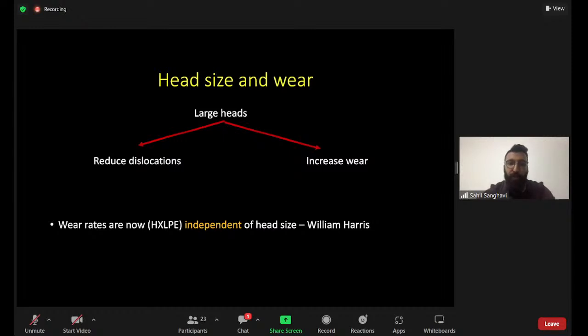Now, the main problem here with polyethylene was the correlation of head size and wear. As we all know, when you use a larger head in total hips, you're always tempted to use a larger head because you know it's going to give you good stability and reduce dislocations. But the problem with larger heads was an increase in the wear. However, with the advent of highly cross-linked polyethylene, they say that wear rates are now independent of the head size.